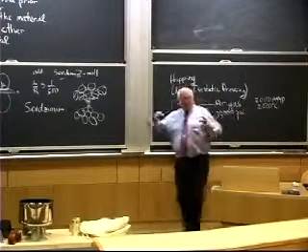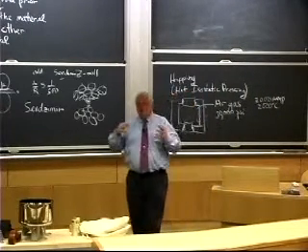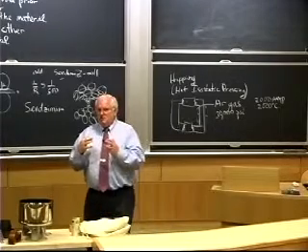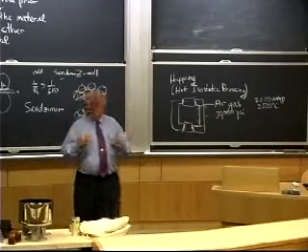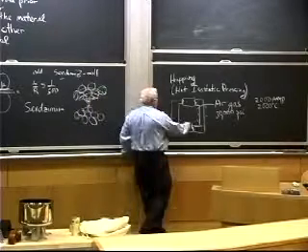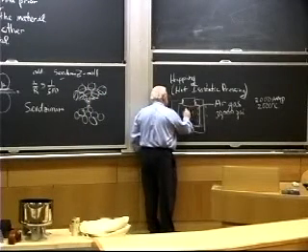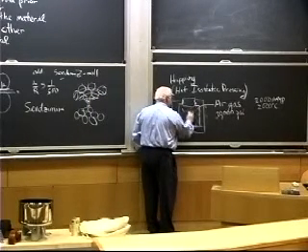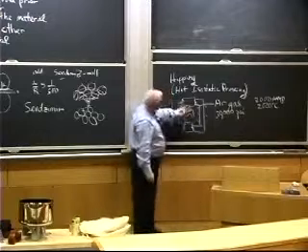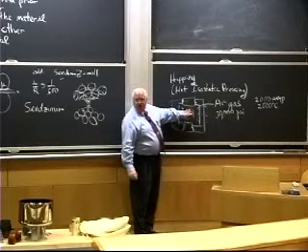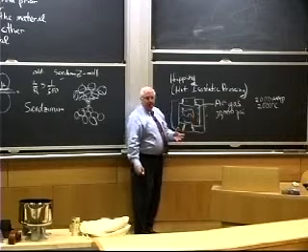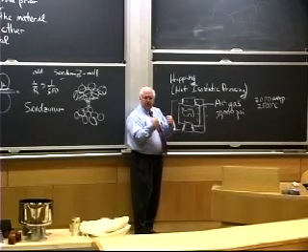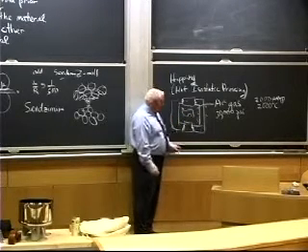So you basically can forge the material and close up those defects and pores without changing the shape of the material, because you're doing it isostatically. The pressure is uniform in here. You've got a gas surrounding it. So if I have a complex shaped part in here, the gas just squeezes it at high temperature. It's like forging it without changing the shape. You're just pressing it, and the high temperature is allowing the metal to creep and deform.